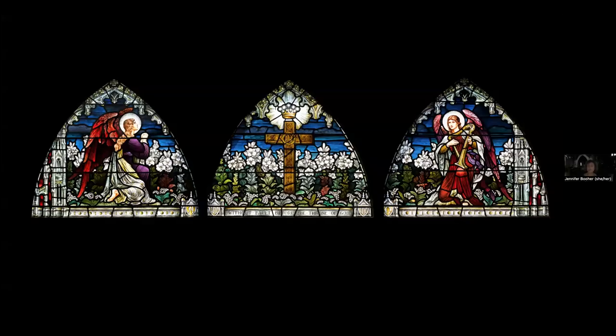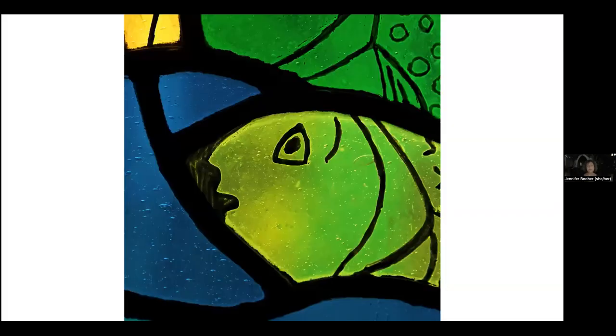What we refer to as stained glass often incorporates all of these techniques in one window. Now there are a lot of different kinds of glass, but the three relevant ones here are antique, cathedral, and opalescent. In the early 19th century, glass makers began trying to recreate the colors and textures of medieval glass and developed various types of handmade glass known as antique glass. In this case 'antique' refers to a style of glass and not its age — it's usually hand blown, thick, and usually has bubbles and other inclusions and imperfections that refract the light and make it more sparkly and deeper colored.